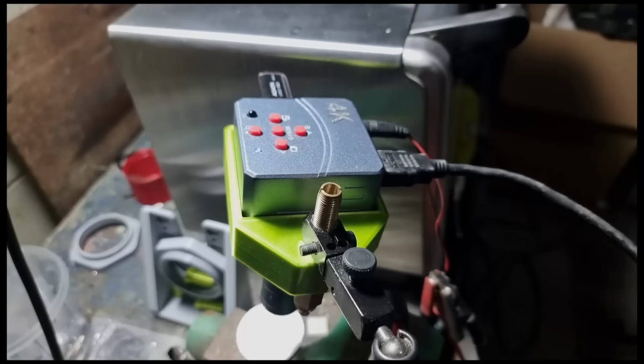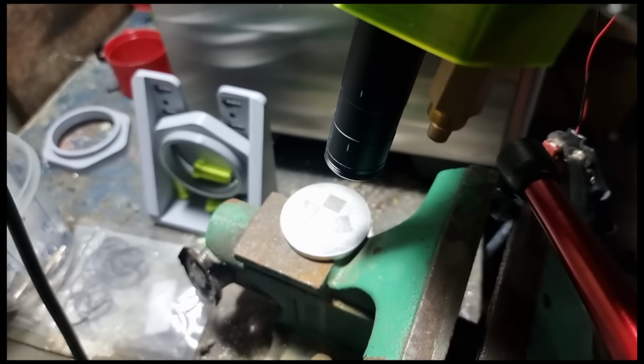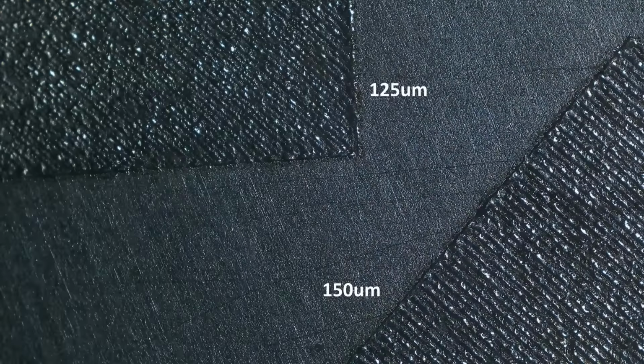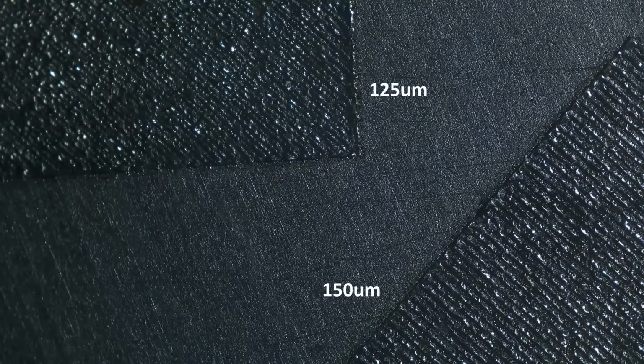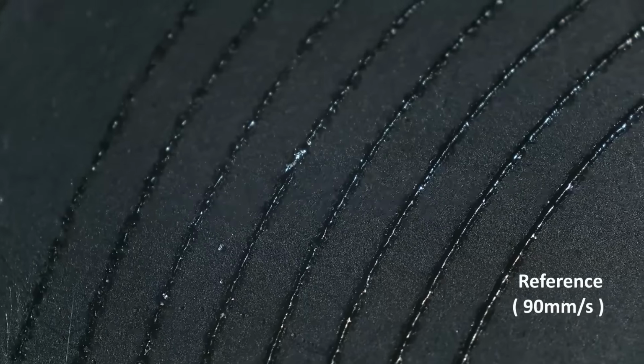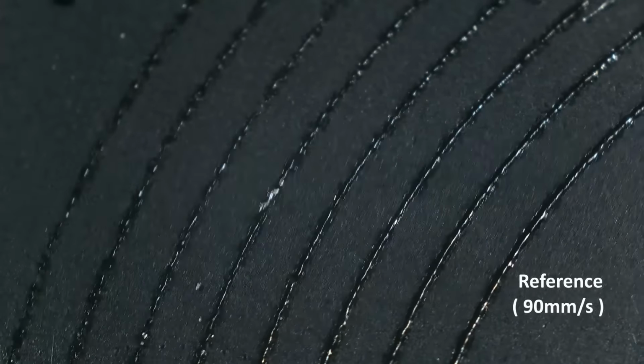My next move was to embark on the second dimension, taking the print speeds that had yielded nicely formed tracks and testing them against the different hatch spacings. I began with a series of tests with hatch spacings ranging from 25 to 150 micrometers, all conducted at a conservative 90mm per second and just following a typical zigzag pattern. At hatch spacings of 150 to 100 micrometers, the irregularities were pretty apparent, but not unexpected. They did help identify the effect of powder disturbance in comparison to the individual tracks though.